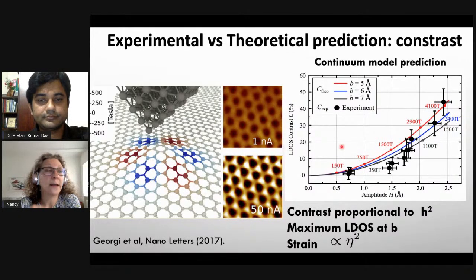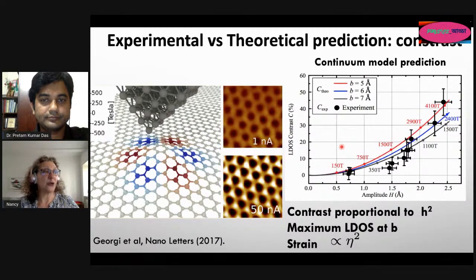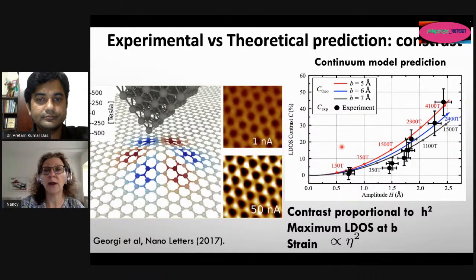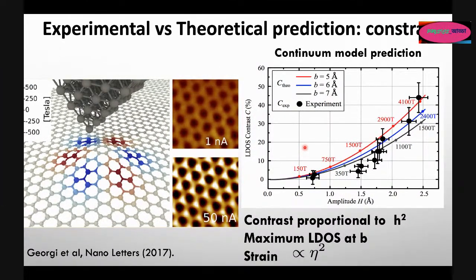So we did the model, we solved the model numerically, we solved the model in the continuum limit, that is using the Dirac Hamiltonian and the matrices that I was referring to at the beginning, and the Dirac equation, and we were able to come up with a formula, an equation that can predict the difference in contrast between the image taken for one sublattice in the deformed region versus the pristine region. The formula was compared to the experimental data, and we got a pretty good fit.